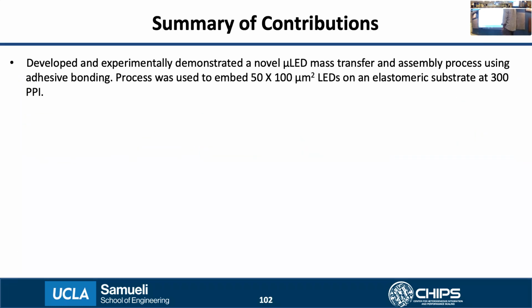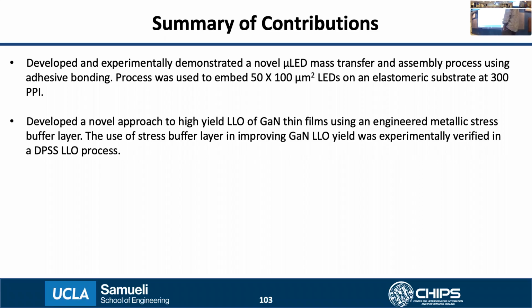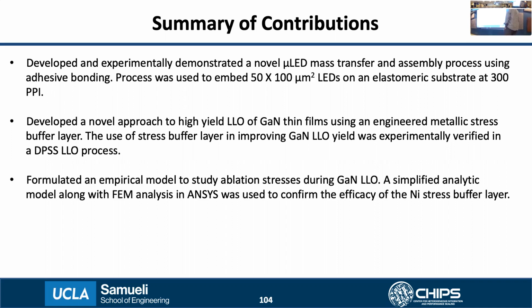So to summarize, here's a summary of my contributions in this research. I developed and experimentally demonstrated a novel micro LED mass transfer and assembly process using adhesive bonding, which was used to assemble 50 by 100 micron square LED devices on elastomeric substrates at 300 ppi resolution. I had also developed a very novel approach for high-yield gallium nitride laser lift-off using an engineered metallic stress buffer layer. The use of the stress buffer layer in improving this LLO yield was also experimentally verified in a DPSS LLO process. I had formulated an empirical model to study the ablation stresses during the GaN LLO process, wherein a simplified analytic model along with FEM analysis was used to confirm the efficacy of the nickel stress buffer layer to prevent the cracking of these devices during LLO.